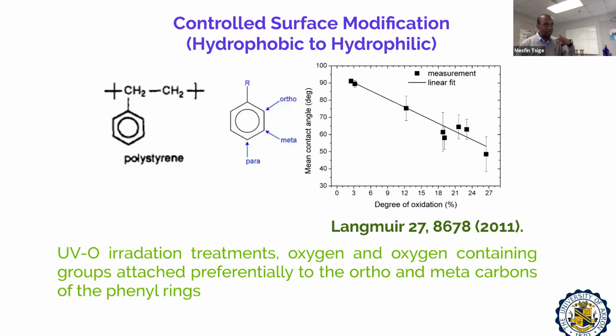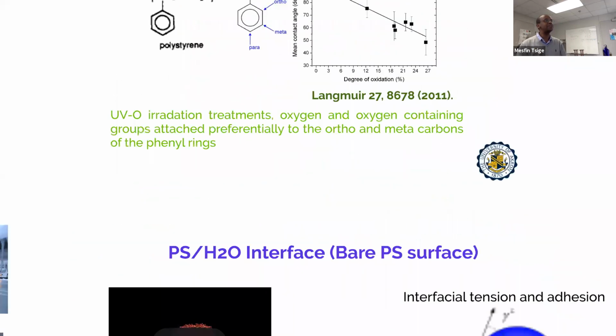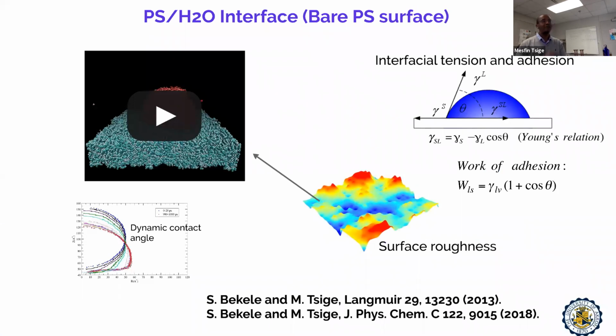In our case, we pretty much first simulated this experimental procedure. We have done the same approach. We took a polystyrene film. All the details, each of the atoms, carbon and hydrogen, are included. And we have also characterized what kind of surface we have. That means when we do mapping where the top atoms are, this is a higher position, the blue is a shallow position, and we have observed a roughness of about 6 to 10 angstrom. This is more like doing AFM on the experimental side.